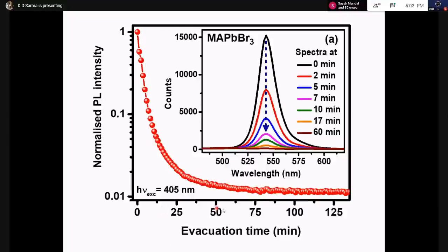As a function of evacuation, we found that the emission peak is getting quenched very rapidly, and emission intensity becomes almost completely zero very, very quickly. This emission intensity area from the spectrum I've shown you is plotted over here, and you can see how rapidly, in a log scale, mind you. If I did it not in log scale, you would have seen it going down vertically, absolutely. In a log scale, it becomes less than 1% very, very quickly. That means something's going wrong when I evacuate.